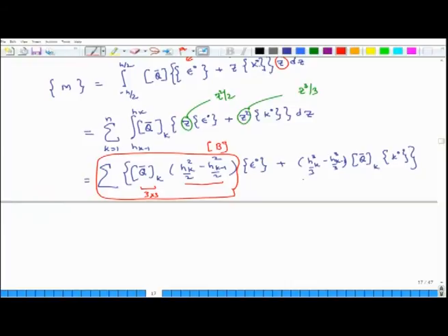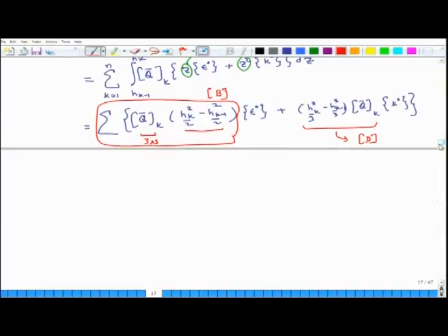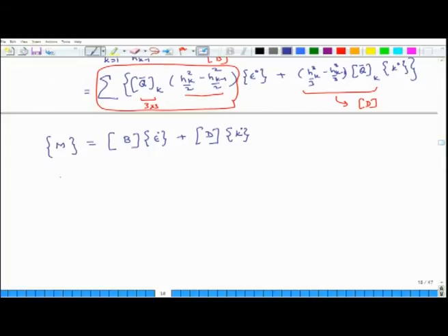Similarly, if you sum up this other thing, it gives you another matrix we will call the D matrix. So, I can say that the moment resultants Mx, My, Mxy are nothing but a 3 by 3 matrix B times mid plane strains plus a 3 by 3 matrix called D times mid plane curvatures. We will write this more explicitly.